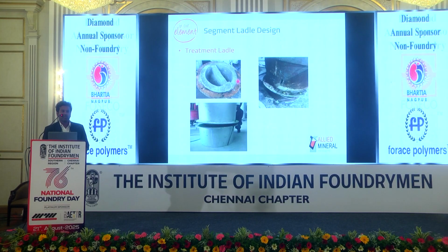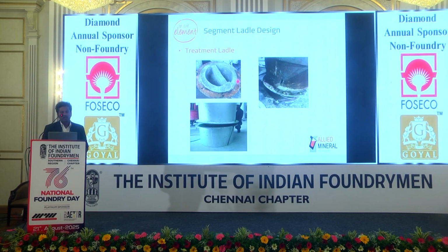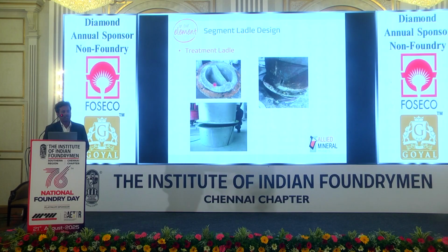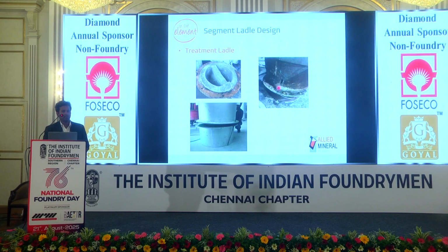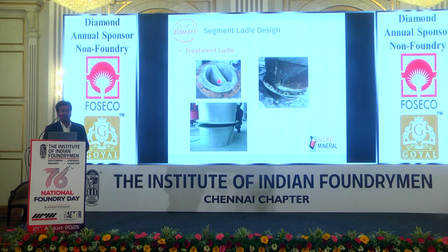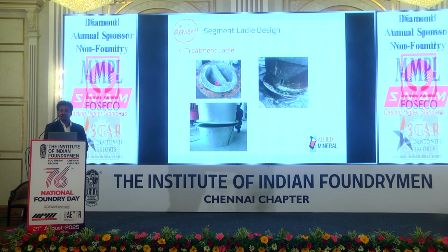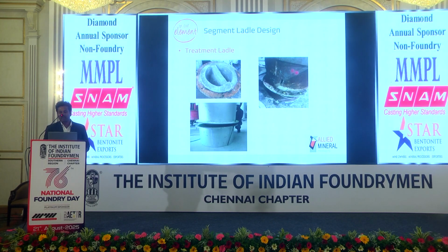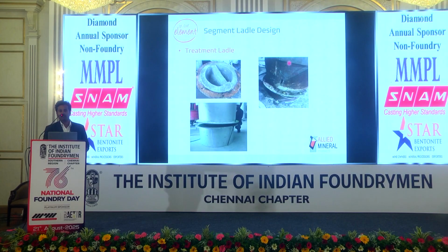So what we can do is segment the ladle into 2 pieces. We can have a treatment pocket separately and attach it to the upper shell. In this way, we can have proper access to the treatment zone for repair. Moreover, we can also repair the upper shell easily.